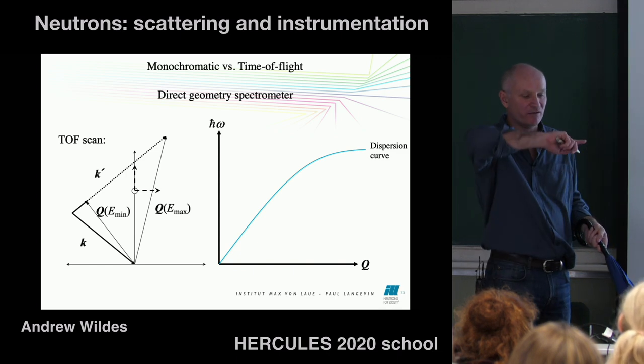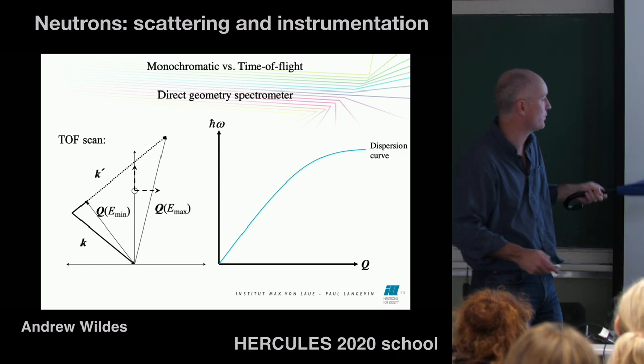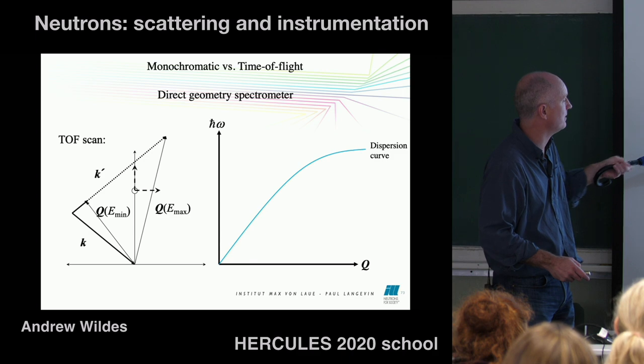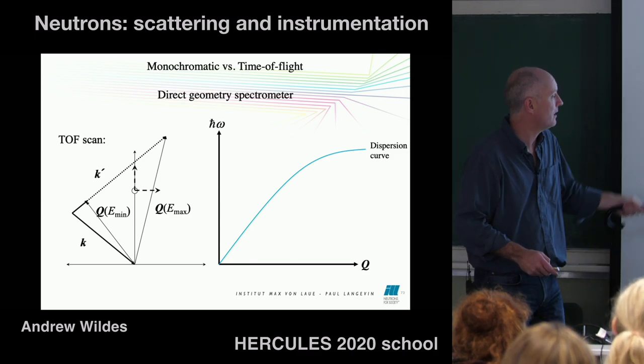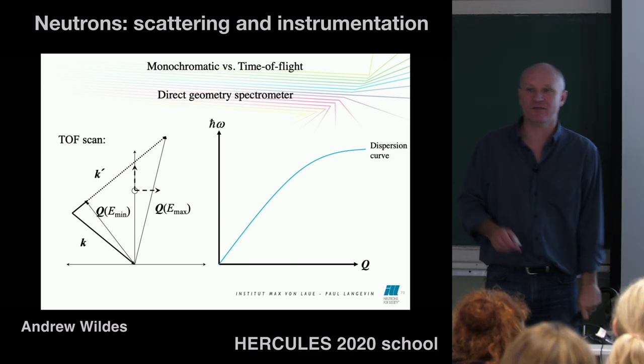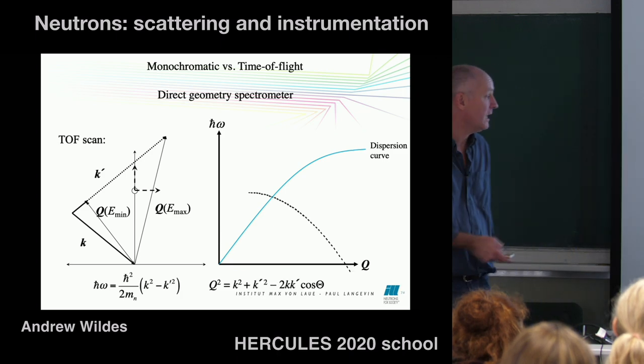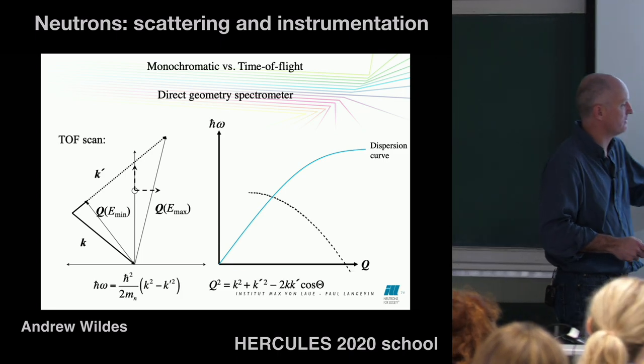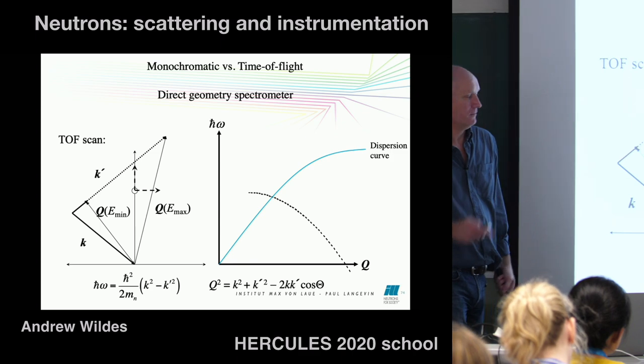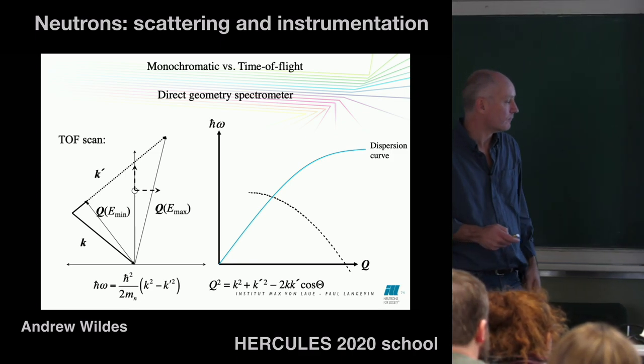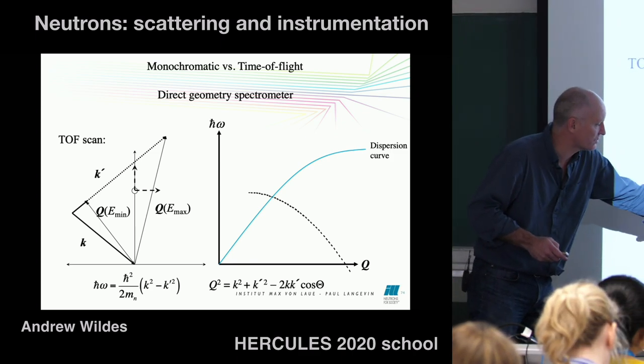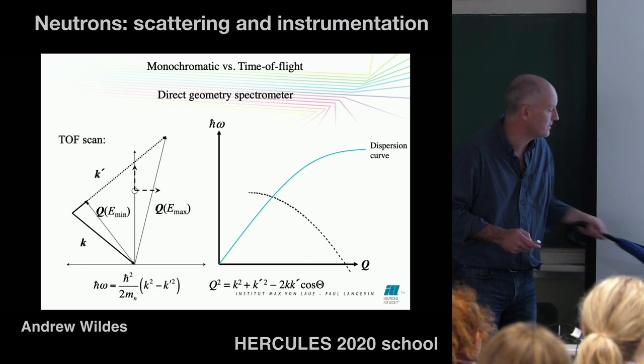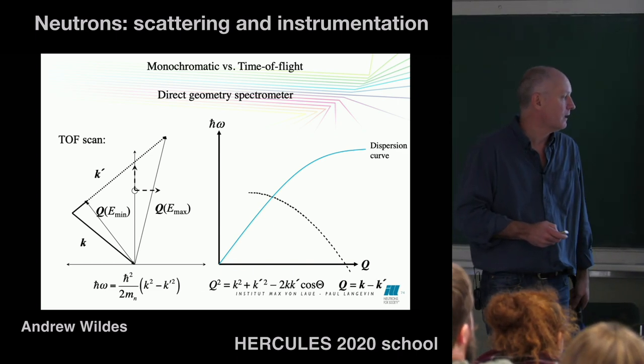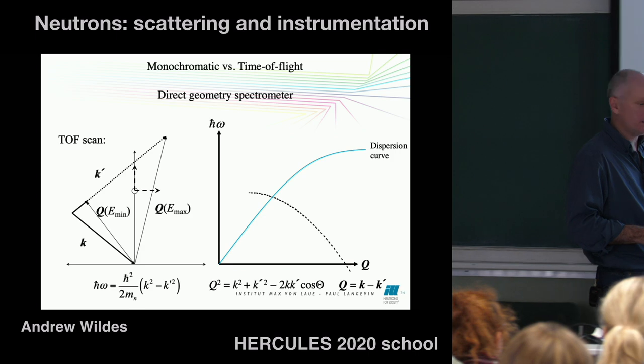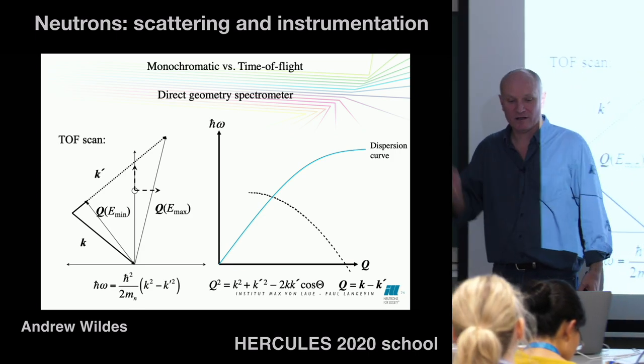But it also has a sort of an energy trajectory associated with it as well, right? Because the energy transfer here is different to the energy transfer here. And you've still only got one point there at the Q that you're interested in. In fact, this shows you the sort of trajectory that this follows in that particular direction there. You can also calculate it using the cosine rule there or this expression for the energy transfer. You do have to worry, though, about the direction of the vector.